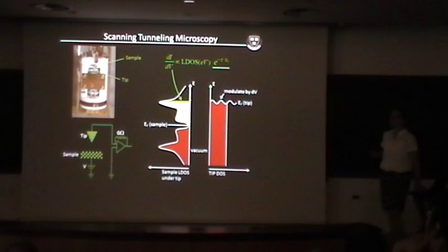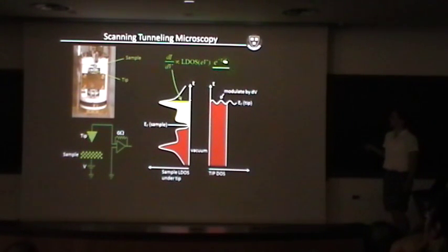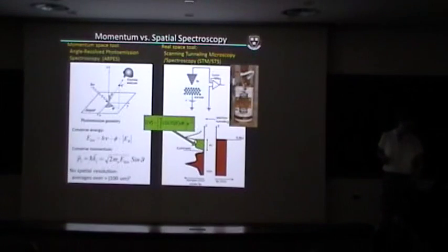Okay, so there's one more factor in this tunneling current here. The differential conductance is proportional to the density of states, which interests us, and the distance between the tip and the sample, which doesn't particularly interest us because it's dominated by who's walking around on the floor upstairs, etc. So this is the term that we don't particularly like. It means that the STM experiment is exponentially sensitive to vibrations. So STM is a very delicate experiment.